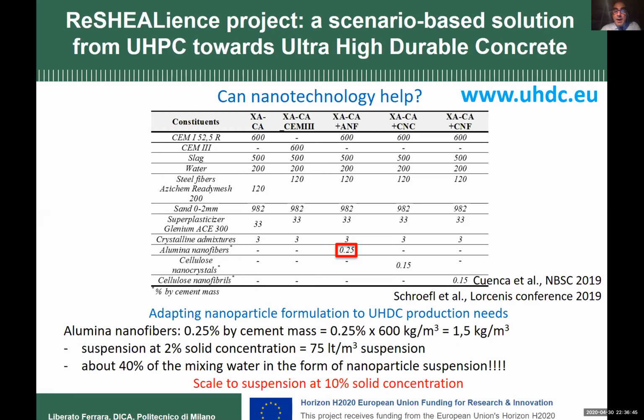But in our material, if you look at the mix design table, at the water line, we had only 200 liters of water. If 75 of them have to go in with the nanofibers, you would never be able to mix this material, because your mix would be very, very stiff.